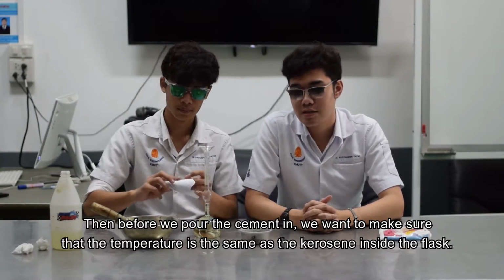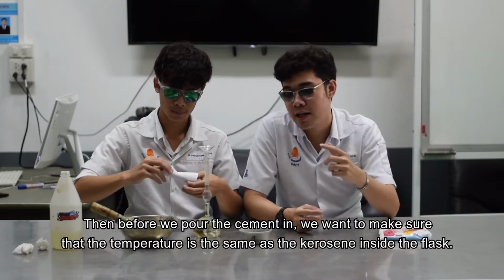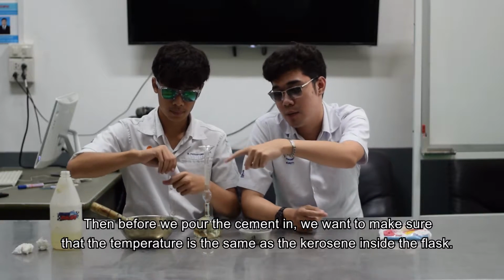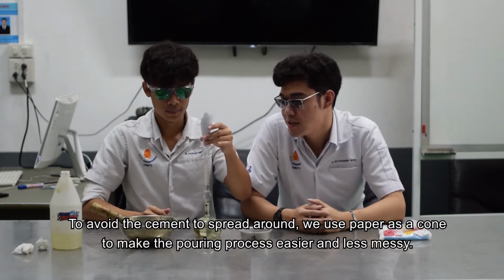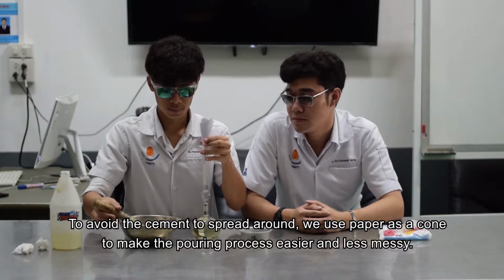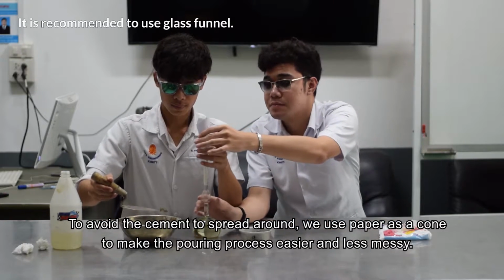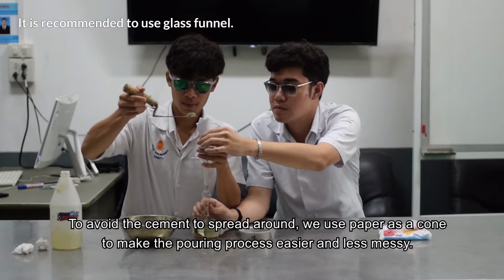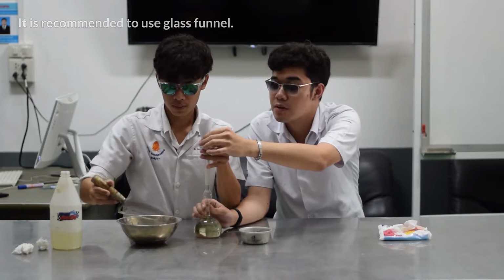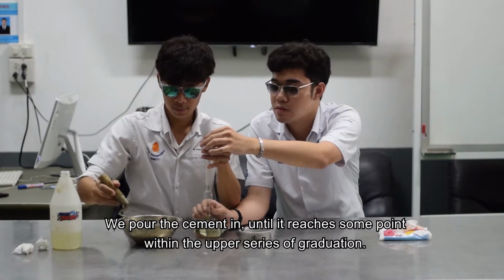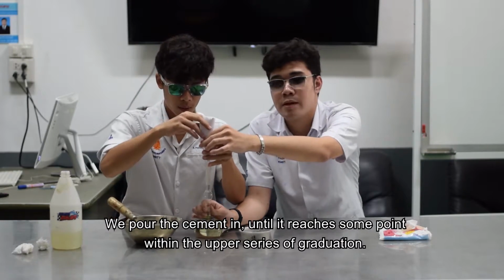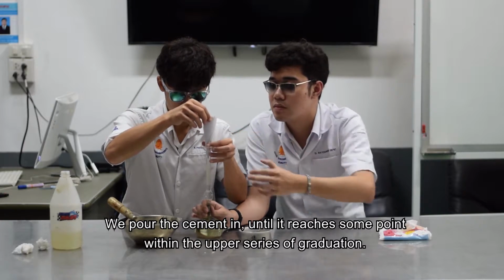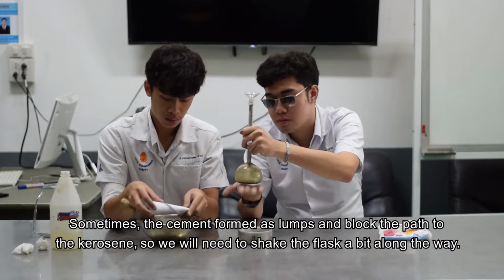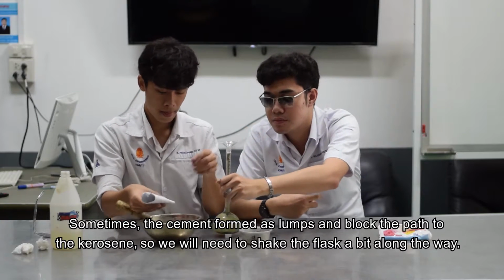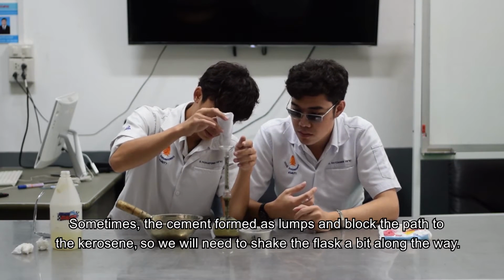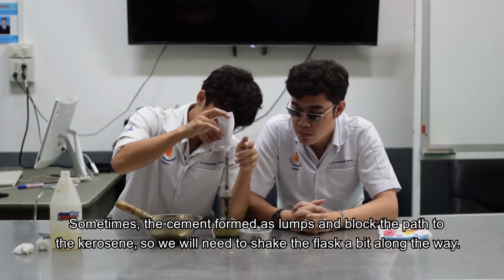Then before we pour the cement in, we want to make sure that the temperature is the same as the kerosene inside the flask. To avoid the cement spreading around, we use paper as a cone to make the pouring process easier and less messy. We pour the cement in until it reaches some point within the upper series of graduation. Sometimes the cement forms lumps and blocks the path to the kerosene, so we will need to shake the flask a bit along the way.